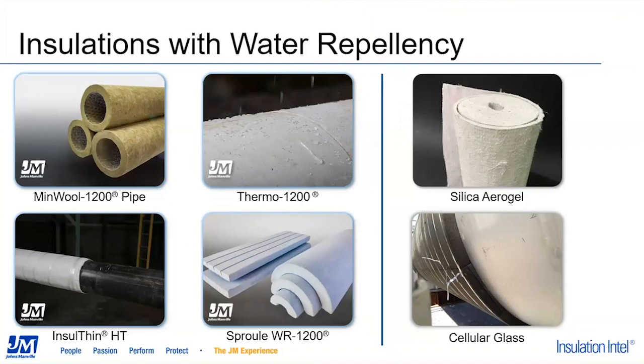The Insulthin HT and Sproule WR 1200 perlite are both hydrophobic products. In addition, most of the silica aerogel products that are available are considered hydrophobic, as well as cellular glass insulation, very often used in ambient and below applications, where cellular glass is considered to be a zero perm material. However, you do need to pay very specific consideration to the seams, as the seams and joints obviously will not be impermeable to moisture and water.